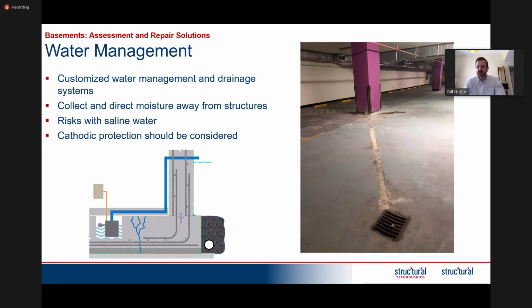Now, the risk in this region is that the water, as we discussed yesterday, or groundwater, has an extremely high salt content. So wherever you are allowing this water to come in, if it's in contact with the concrete, it could lead to a durability related problem. So really you should carefully consider whether water management is required or not. And if it is required and you're looking for a long-term solution, then possibly you need to include some corrosion control as well, such as cathodic protection.